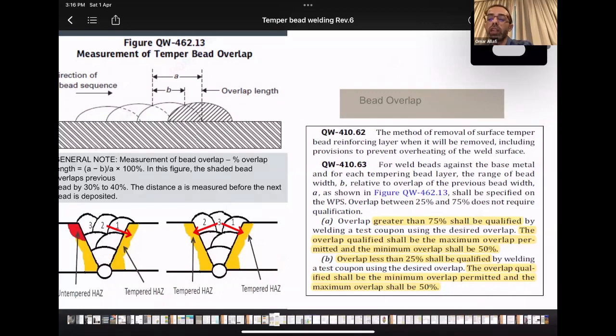Similarly, when you are using a lower overlap value, like less than 25, you need to have a new test coupon that is matching the new overlap value. Let's say that it's 20, and your maximum overlap in this case will become 50%.